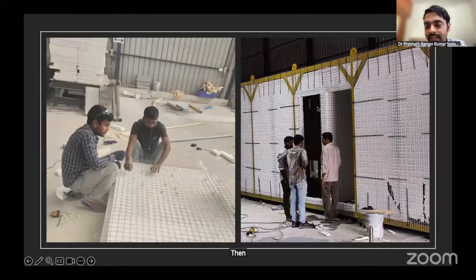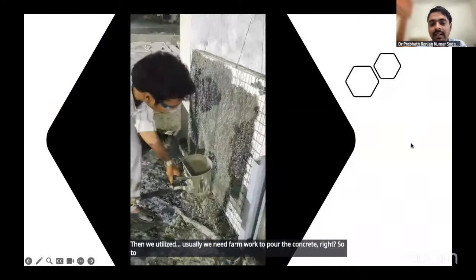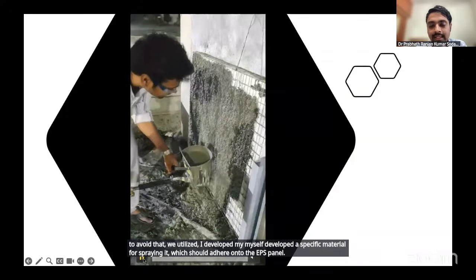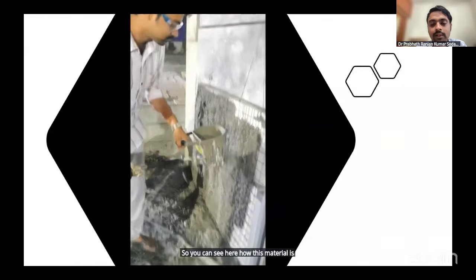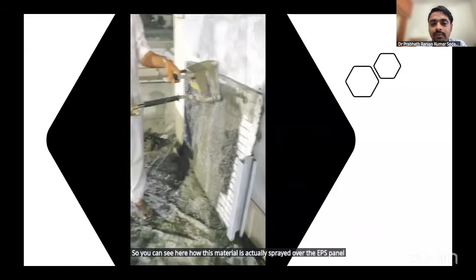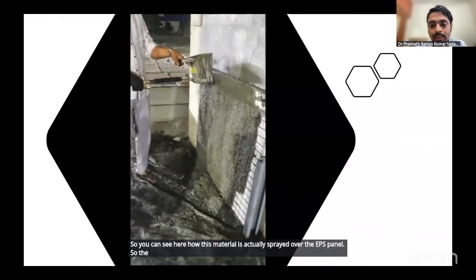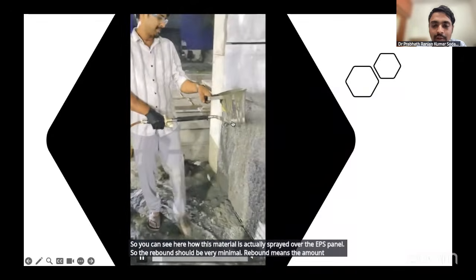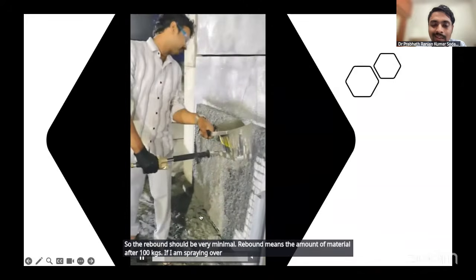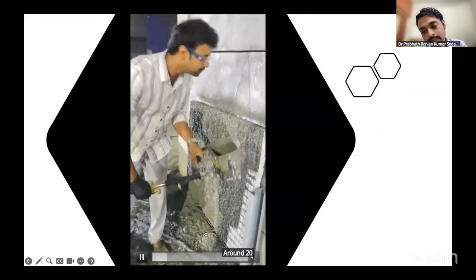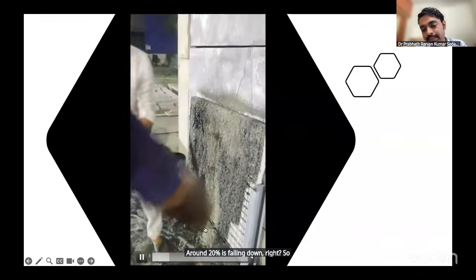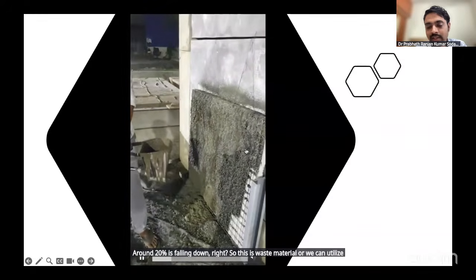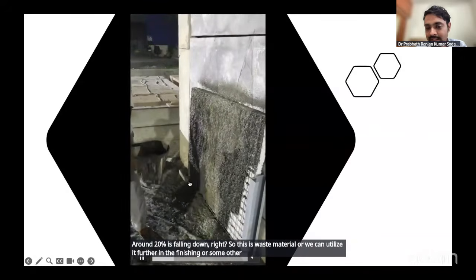Then we utilized, usually we need formwork to pour the concrete, right? So to avoid that, I myself developed a specific material for spraying, which should adhere onto the EPS panel. So you can see here how this material is sprayed over the EPS panel. The rebound should be very minimal. Rebound means the amount of material that, out of 100 kgs sprayed over the panel, around 20% falls down. This is waste material, or we can utilize it further in the finishing or some other aspects of the construction.